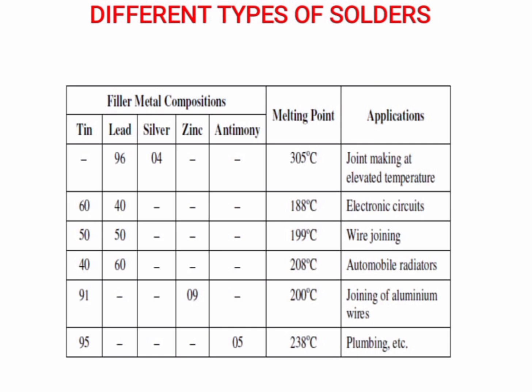Tin 50 and lead 50, which have a melting point of 199 degrees centigrade, is used for wire joining. Tin 40 and lead 60, which has a melting point of 208 degrees centigrade, is used for automobile radiators. Tin 91 and zinc 9%, which have a melting temperature of 200 degrees centigrade, is used for joining aluminum wires. Tin 95 and antimony 5%, which have a melting point of 238 degrees centigrade, is used for plumbing applications.